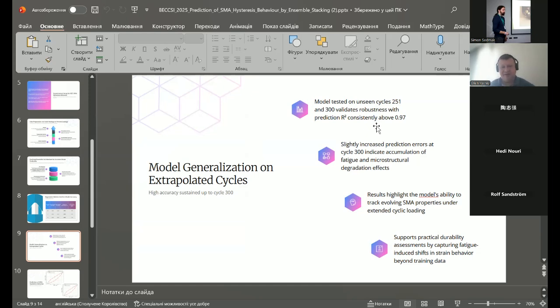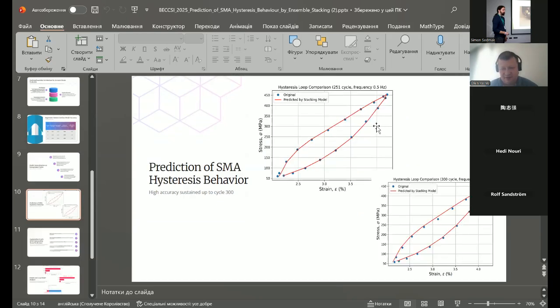The model was tested on unseen cycles 251 to 300. This validates robustness as R-squared is consistently above 0.97. Slightly increased prediction errors at cycle 300 indicate accumulation of fatigue and microstructural degradation effects. Results highlight the model's ability to track evolving SMA properties under extended cyclic loading. They support practical durability assessment by capturing fatigue-induced shifts in strain behavior beyond training data.